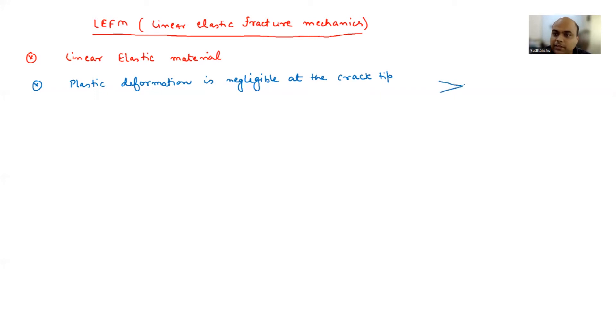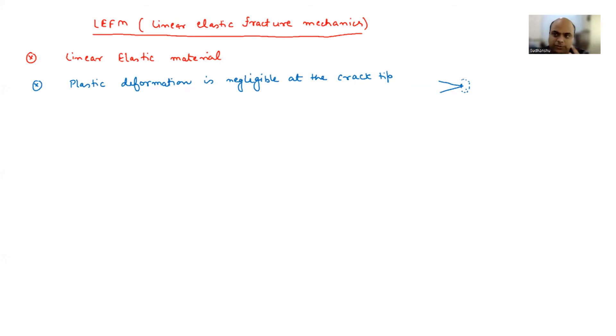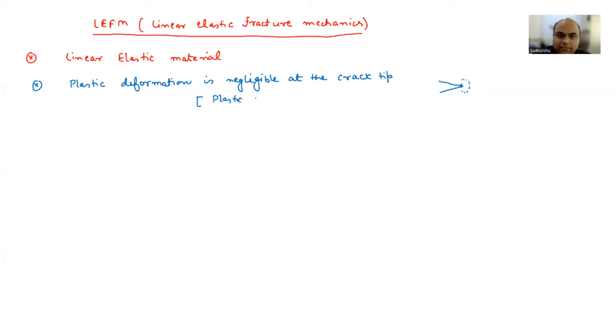Suppose you have a crack — whatever plastic deformation you are getting there, that region we generally call the plastic zone. The plastic zone is much, much smaller than A, where A is the crack length, or half crack length depending on the configuration. That is what I mean by plastic deformation being negligible.